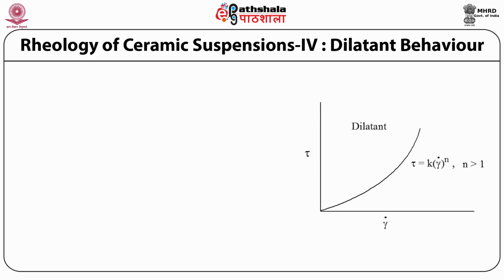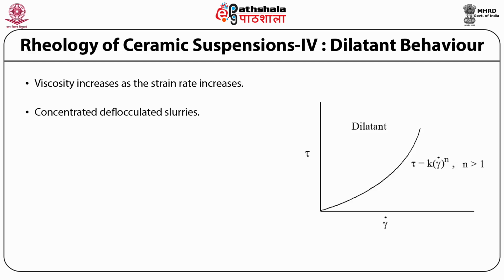Now the next behavior is dilatant behavior. Here the apparent viscosity, that is eta A, increases with increasing strain rate, so that the slope of the strain rate versus shear stress plot increases with increasing strain rate, as can be seen from this figure. This behavior is characteristic of concentrated deflocculated slurries.